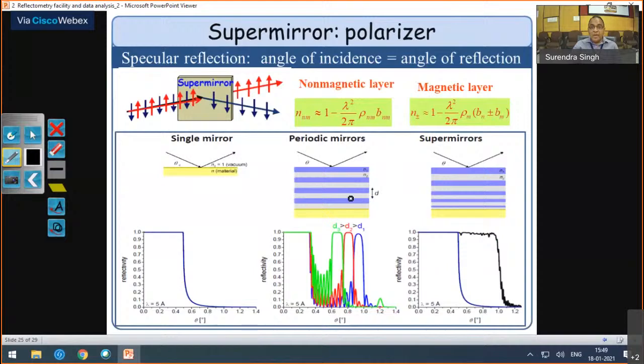If you make many multi-layers on one sample, depending on the period D1, D2, D3 — suppose you have three multi-layers in the same structure with different periods, like nickel-copper, where D1 is the bilayer thickness, say 50 angstrom plus 50 angstrom, and another bilayer combination is 60 angstrom plus 60 angstrom.